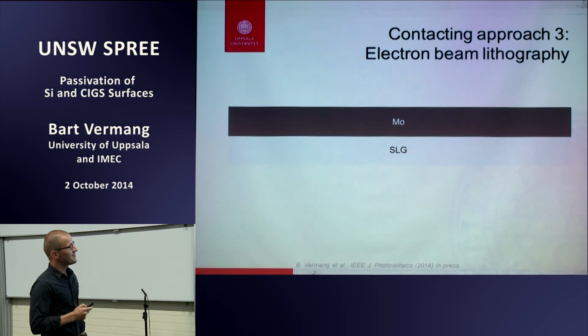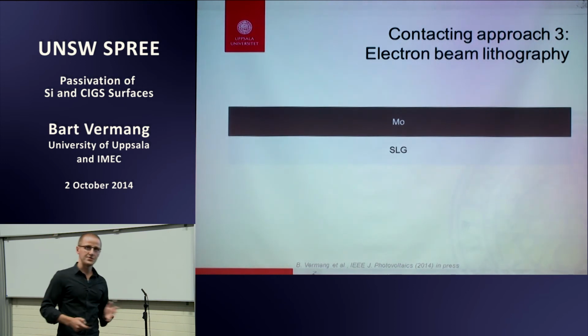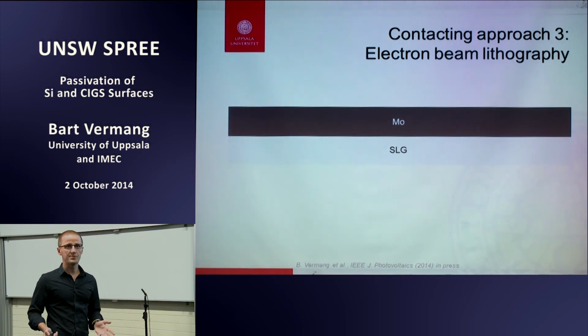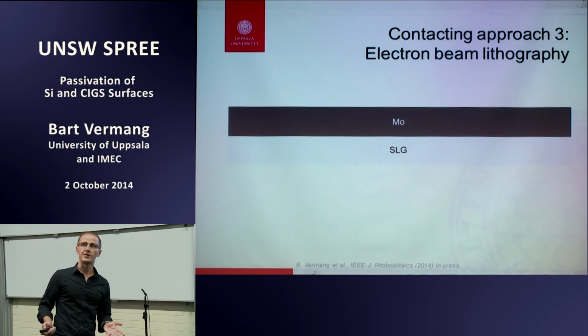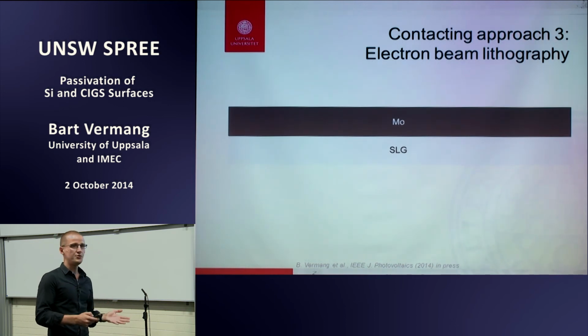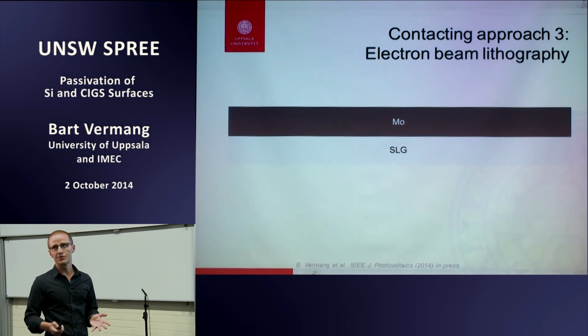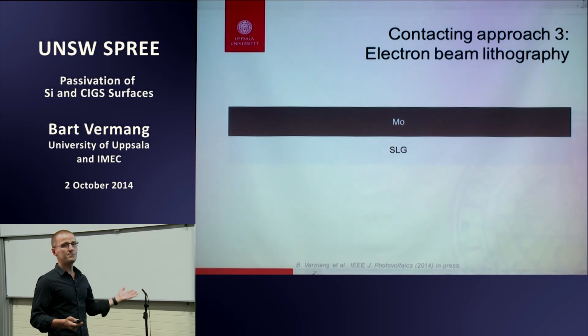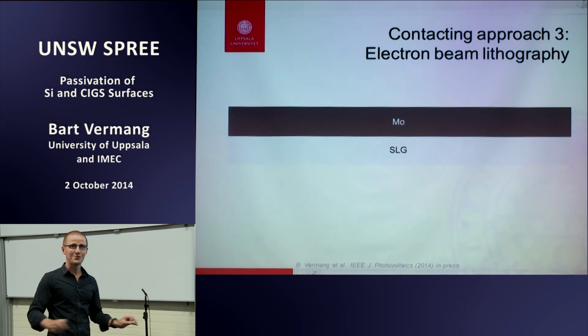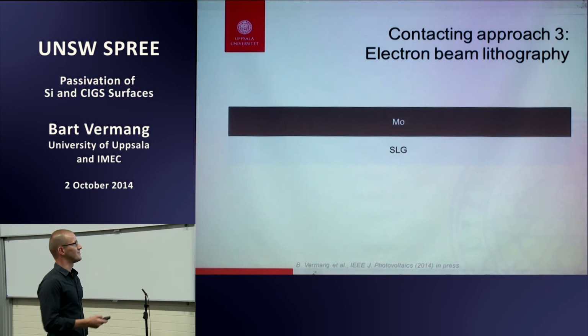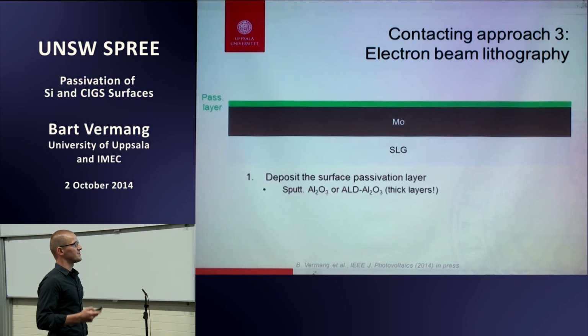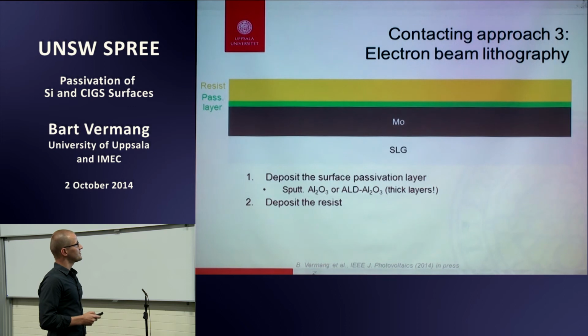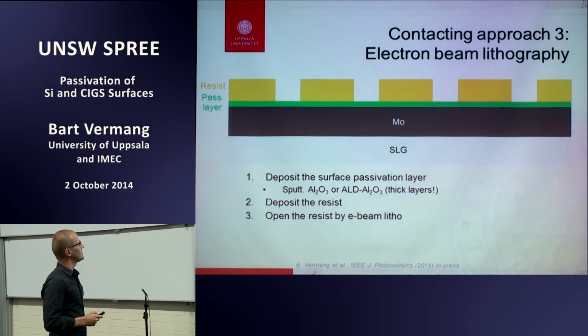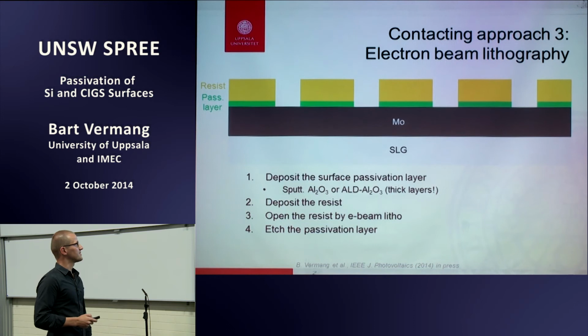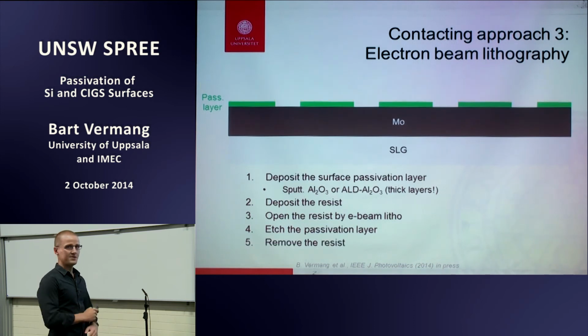The third one: the last two were more to have a proof of principle, to show, look, this can work, and to say what we are doing might be industrially viable in the long term. But we also need study devices. So we also have been using electron beam lithography to make nicely controlled grids. And that's a perfect study device. So in this case, you deposit the passivation layer, you put some resist, you open the resist by E-beam lithography, you etch away the rest of the passivation layer, and you get a nice controlled grid.